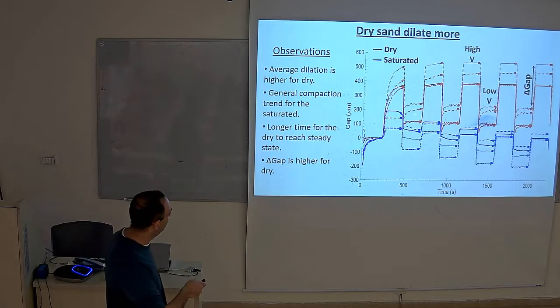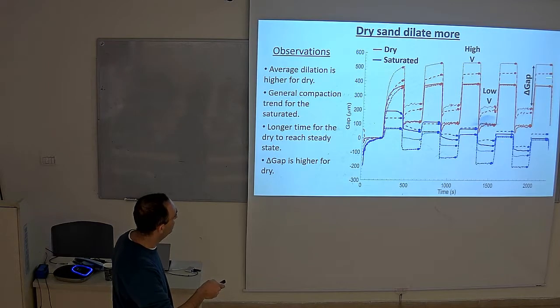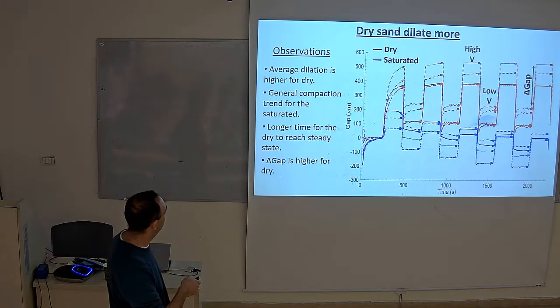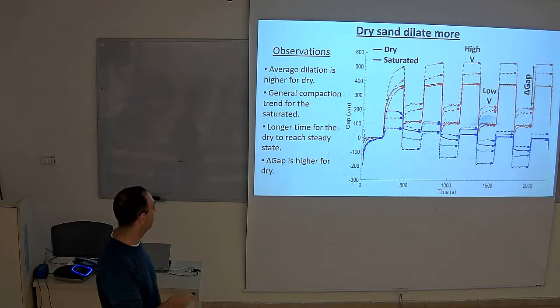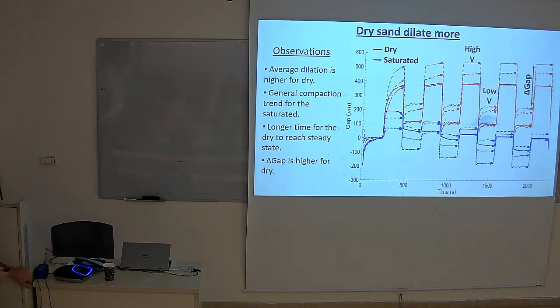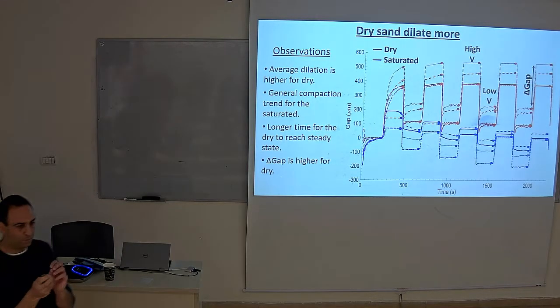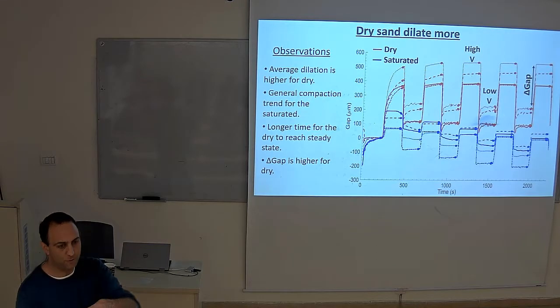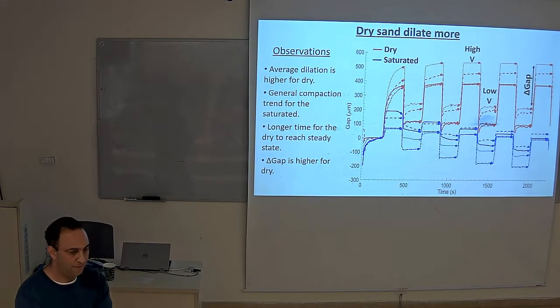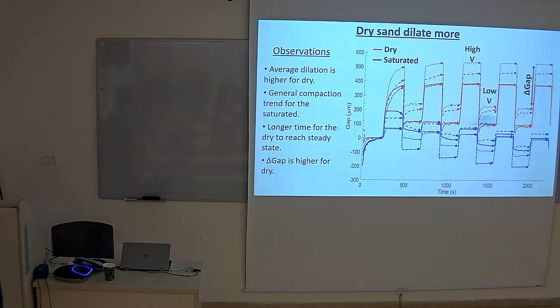You see, if we look even at the low velocity experiment and high velocity in general, we see a dilation pattern. While for the blue, for the wet experiment, we see even compaction. I will talk about this compaction. This may be explained by a little bit increasing pore pressure between the grains, and it's easier for them to slide and to find a better compaction in a wet system. The other thing is the general compaction, and I will touch on it when I show you some videos of the experiments.